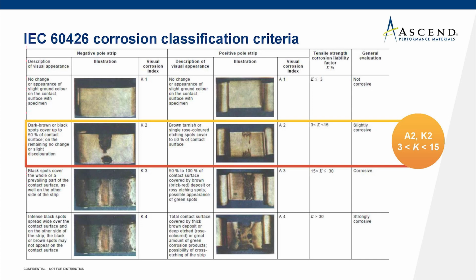And then there's also a K factor, which is the quantitative aspect in the column second from the right, and this is represented by how much the tensile strength of that metal strip diminishes after heat aging versus its initial unaged value. For both of our heat stabilizer grades, we're able to achieve an A2K2 grading, which is slightly corrosive. And this is comparable to competitor materials in the same class.